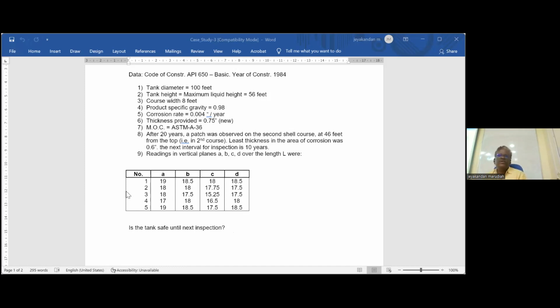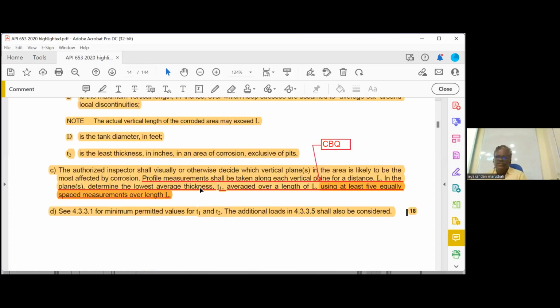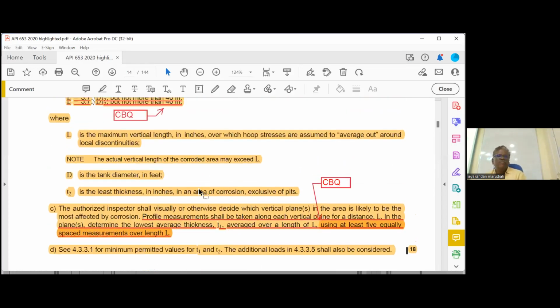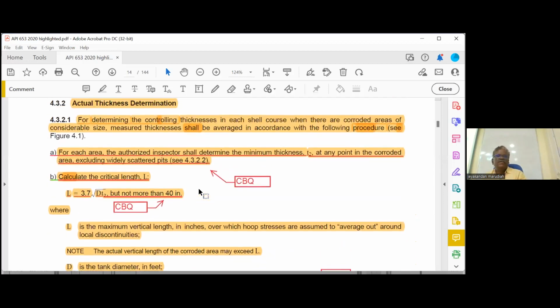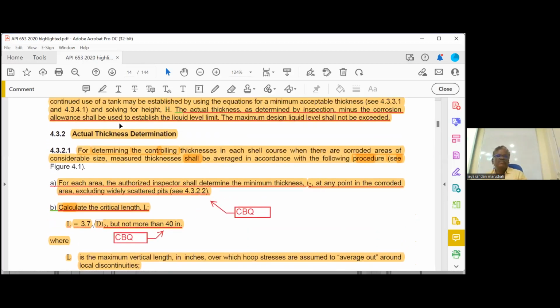Okay, so now we have T2 of 0.6 inch and T1 of 0.67 inch. Where is it given? Let us go to the code book, because I told you we will go part by part in the code. Now start from here. So for actual thickness determination, please take 4.3.2 in the code book. For determining the controlling thickness of each shell course, when there are corroded areas of considerable size, measured thickness shall be averaged in accordance with the following procedure.